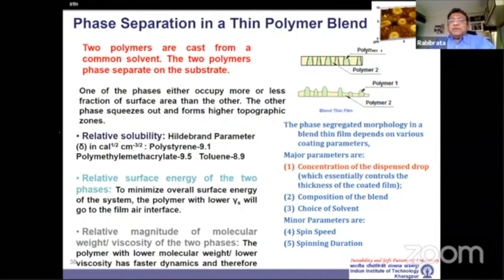And this is related to polymer blends, something Manish knows very well. If you mix 2 polymers and just cast them from a common solvent, you directly get some phase separated morphology. It's because 2 polymers, let's say if they're symmetric 50-50, do not both occupy 50% of the space. There will be differences in their solubility, their affinity, and their molecular weight. Because of a variety of reasons, one phase will occupy more than its designated amount. Let's say one phase will occupy 60% of the surface. Therefore, the remaining 50% will be cramped into 40%.